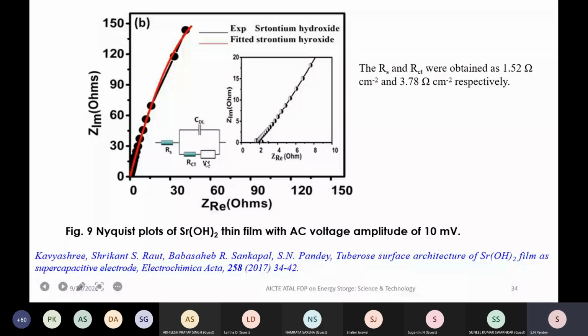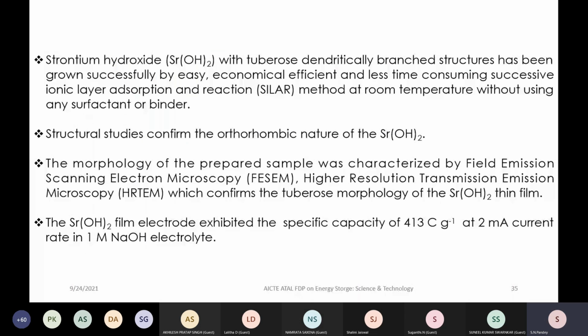So let us summarize what we have done. We obtained the strontium hydroxide tuberose structure with the help of this SILAR method, and the structural study confirms the orthorhombic nature. It has a value of 413 coulomb per gram at 2 mA current rate in 1 molar NaOH electrolyte. We have to fix the electrolyte, the number of cycles and so on. So the obtained value is 413.